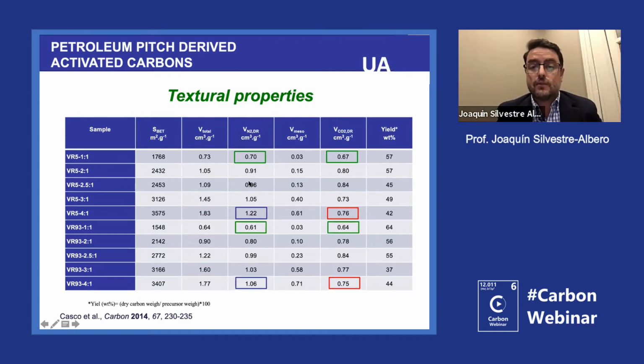However, for the samples with a very low activation degree, the surface area is also quite good. We are at more or less 1,500 to 1,700. And you can see that nitrogen and CO2 are very coincident. So that means that in these materials, as I was showing before, the porosity is extremely narrow. And that's why you have this narrow knee in the nitrogen isotherm.